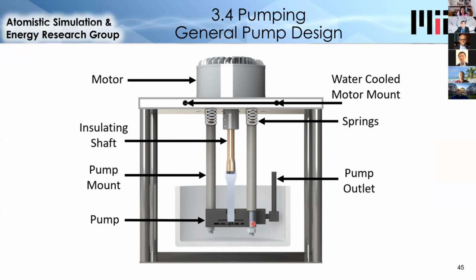However, when the pump is heated from room temperature to 2000 Celsius, these sleeves, these hollow pipes, expand vertically about 5 millimeters, while the bolts don't expand much at all. And the effect is that a large stress is developed. And so this is accommodated with the springs shown here that are in series with these pipes. So when the pipes expand, the springs are compressed. And this prevents a large stress from developing.